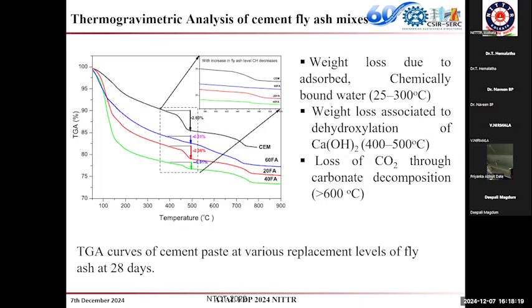And this is just to show some of the tools we can use for identifying what is happening when we are using fly ash at different replacement levels. This is when we are doing cement hydration. This portion refers to the formation of calcium hydroxide. When we talk about strength, the strength of concrete is promoted by the formation of calcium silicate hydrate. The calcium hydroxide formed reacts with the silicate to form calcium silicate hydrate. Depending upon how much calcium hydroxide, the intermediate product, is formed, the strength can be increased. So here it shows that when we go for high replacement levels, it affects the calcium hydroxide formation.